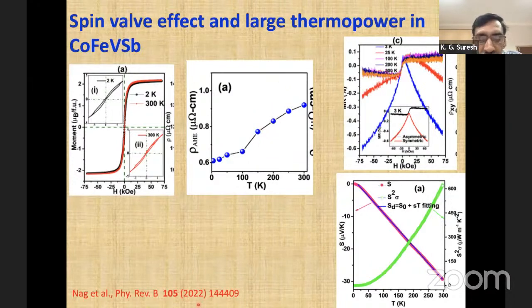This is again very recent data. But interestingly, we would have been happy with this. But then, I don't remember even what was the context of measuring the thermopower here. When we measure thermopower, we find that the thermopower is very unusually large.